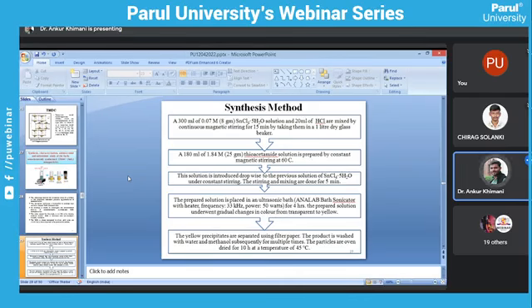The prepared solution is placed in an ultrasonic bath. The specification of the ultrasonic bath is Analab bath sonicator with heater, frequency 33 kHz, power 50 watts. For 4 hours, the prepared solution underwent gradual changes in color from transparent to yellow.